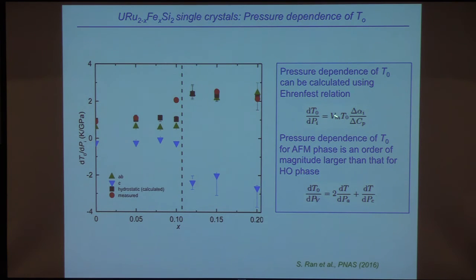And you can deduce these from the Ehrenfest relation. So this is for thermal expansion, these triangles, AB plane, C-axis, and then you can deduce the volume thermal expansion, the volume effect. And then what's shown here from the red points is the actual measurements of these transition temperatures as a function of pressure, okay? And so you can see that you can very clearly define the transition from the hidden order phase into the large moment antiferromagnetic phase.